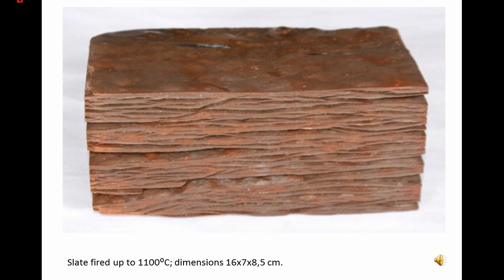Increasing the firing temperature, the black slate piece becomes darker and maintains the rusty red color, but gains in gloss and shows a silky sheen. On the external faces, parallel to lamination, pimples are developed and the other external surfaces become very textured, looking like the bark of some trees. The overlapping laminas lose their original perfect connection, whereas their hardness and mechanical resistance increase. It changes to a less dense and light material.